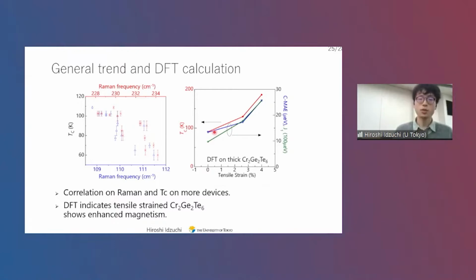Okay, that's a good point. In fact, some groups show enhancement of Curie temperature using the coupling between antiferromagnet and ferromagnet. So we also kind of expected it, but there are some negative data. For instance, I do not see an exchange bias effect, while if we use permalloy and nickel oxide layers in the same chamber, I can actually see exchange bias. So that's why I think what we observed is most likely not from the antiferromagnetic behavior of nickel oxide. But that's a good point.